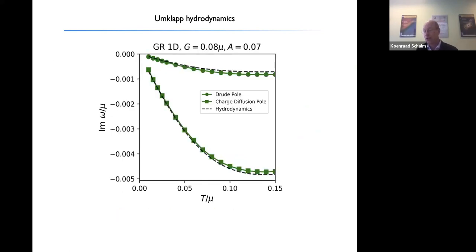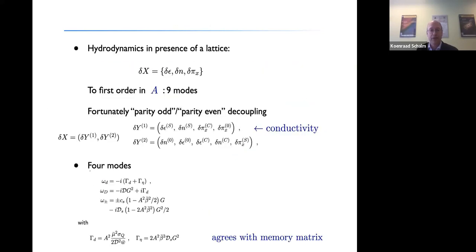You can test this rather precisely because, notice that thanks to the hydrodynamics, you have a very precise prescription of the location of this pole in terms of thermodynamic quantities and transport coefficients, as well as the lattice vector. And so you can very precisely predict where this pole should be simply based on the homogeneous system. And then you put it in the small lattice, and then you can see where it is.